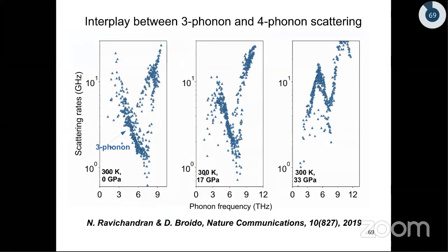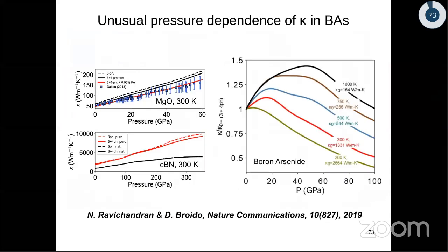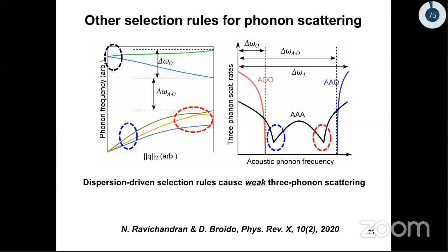It's a very good question. Let me see if I have a backup slide for that. So by joint density of states, I'm assuming you mean this phase space, right? Exactly. So in whichever material we find 4-phonon scattering to be important, there's always a weak 3-phonon scattering phase space, the lowest order scattering. In any material where we find a strong effect of 4-phonon scattering, in strongly bonded materials like III-V compounds, we always find a weak 3-phonon phase space.